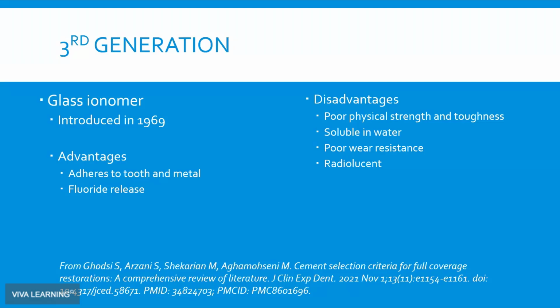Now, granted, in 2001, when I graduated, that was when things just started going into a metal-free, all ceramic approach. That's when it was beginning anyway. Obviously, we were taught shoulders with bevels, and glass ionomer is excellent in that circumstance. But the moment you go to chamfers, these rounded preps with a butt margin, it starts becoming an issue, especially with gap distances greater than 20-30 microns. That makes sense. You use a toothbrush, those bristles go somewhere, and you can brush away a relatively weak material without too much effort. With any subgingival margins, it's very, very difficult to keep the glass ionomer from just dissolving even before it sets.